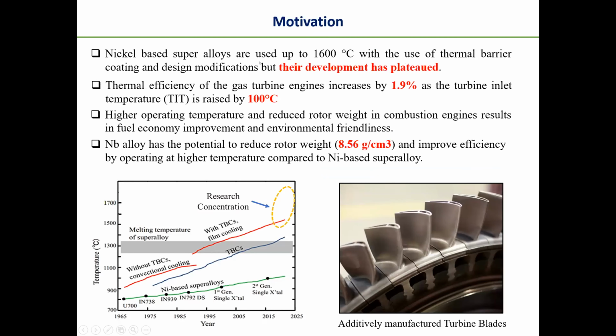Generally, nickel-based superalloys are used for gas turbine blades, which can operate up to 1600 degrees centigrade, but their development has plateaued. The thermal efficiency of gas turbine engines mainly depends on their turbine inlet temperature, which can be increased by around 2% if the operating temperature is increased by 100 degrees centigrade. So higher operating temperature and reduced rotor weight can result in better combustion engine efficiency as well as environmental friendliness. Refractory metals and their alloys have a much higher melting temperature, and they can retain their strength up to much higher temperatures than nickel-based alloys. And among the refractory alloys, niobium has the least density, which is around 8.56 gram per centimeter cube.